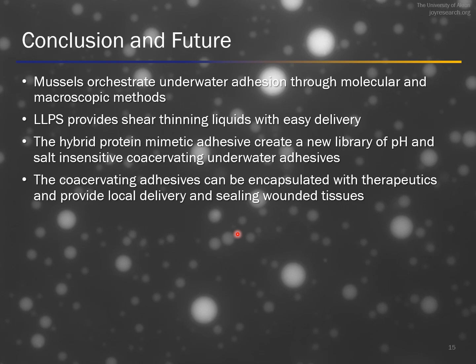So from this talk, I hope everyone learned that mussels orchestrate strong underwater adhesive mechanisms through molecular and macroscopic methods. It has perfected both the chemistry and the delivery of the adhesives in underwater conditions. The polyesters that we have developed are non-ionic in nature, which helps them to be pH and salt insensitive, which has never been reported before in the literature. And we anticipate that the strong adhesive nature of these non-ionic polyesters will help in sealing wounded tissues.